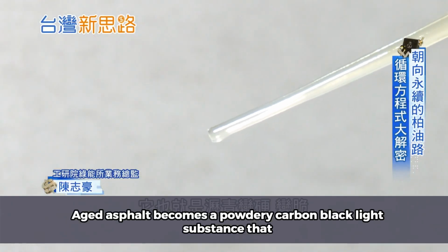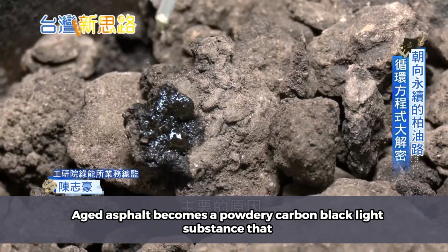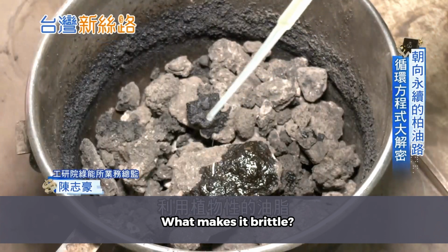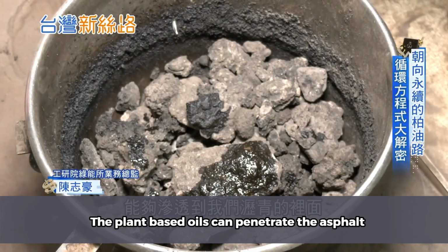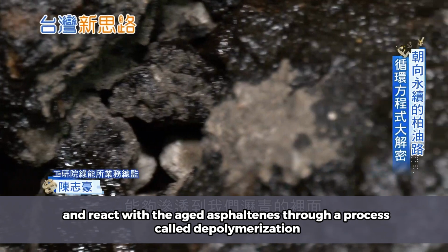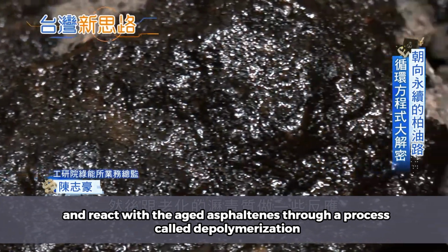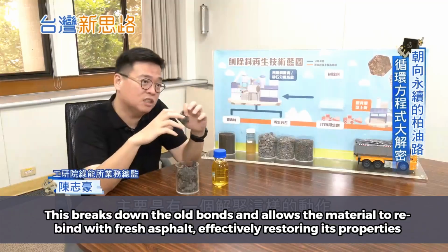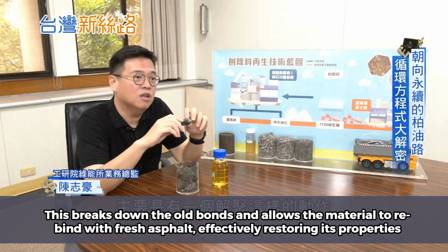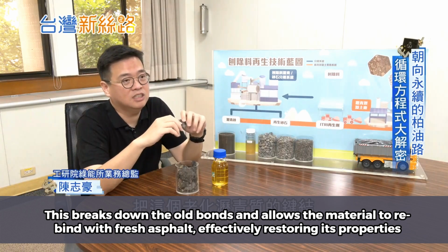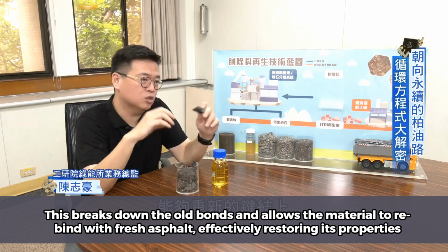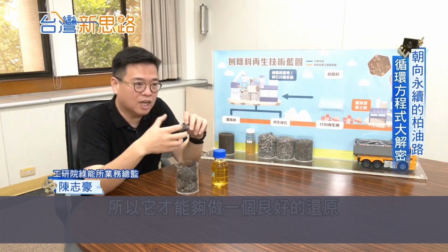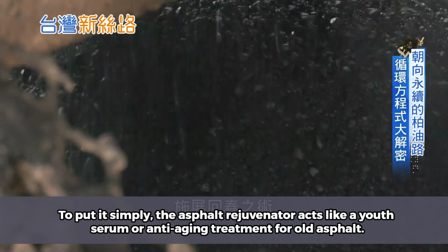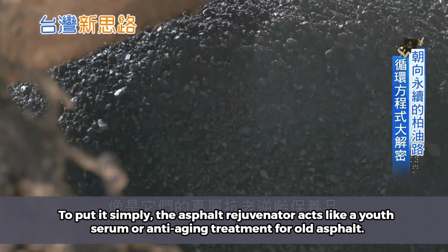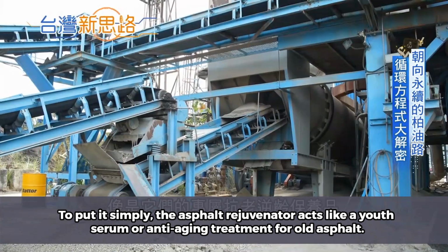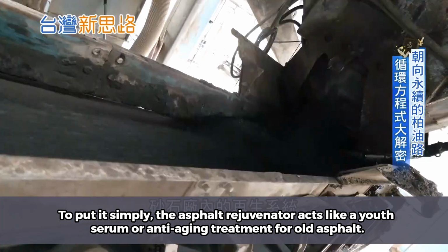Aged asphalt becomes a powdery, carbon black-like substance. That's what makes it brittle. The plant-based oils can penetrate the asphalt and react with the aged asphaltenes through a process called depolymerization. This breaks down the old bonds and allows the material to rebind with fresh asphalt, effectively restoring its properties. To put it simply, the asphalt rejuvenator acts like a youth serum or anti-aging treatment for old asphalt.